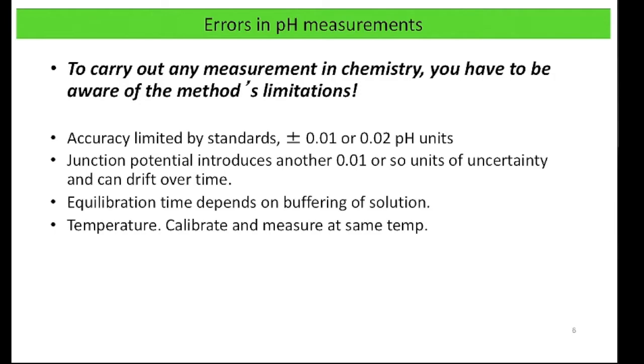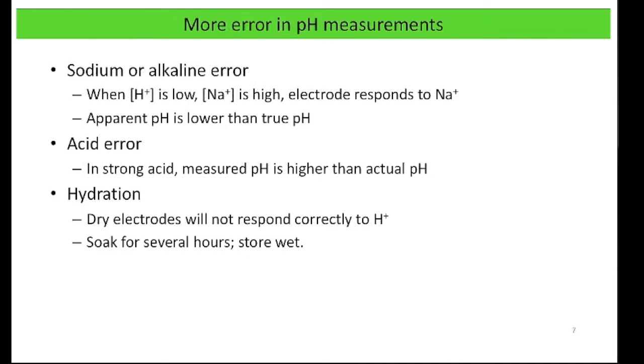measured reliably. And temperature is also going to affect the pH measurement because that's going to affect the equilibrium of any solution that's being measured, even if it's a standard. So measurements must be done at the same temperature, including your calibration standards. A couple other errors. There's one called the sodium or alkaline error. So when the concentration of H plus is low, so we're in a basic solution, say pH 9, 10, 11, for example, but the concentration of sodium is high, the electrode starts to respond to sodium. So sodium ends up being something that interferes with our measurements at low H plus concentrations and high sodium concentrations.